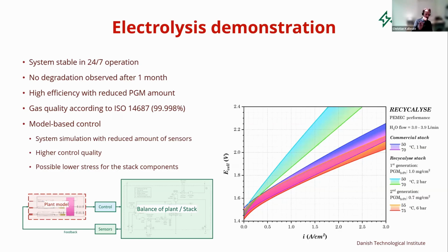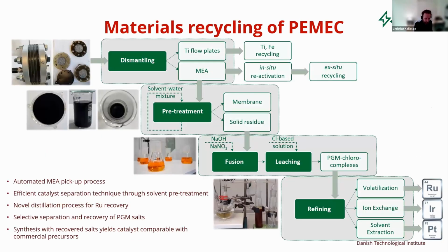And now I can see I'm running out of time. So very briefly, we also looked at the recycling scheme, how to dismantle it, how to separate the catalyst and dissolve it, how to distillate it for ruthenium recovery, refine it, get all the different materials out into different salts that we can then utilize, and then we demonstrated how using these salts we can actually create catalysts with just as good activity as a commercial salt, a precursor, and with a recycling efficiency of over 90%. I think I've used my time, so thank you very much.